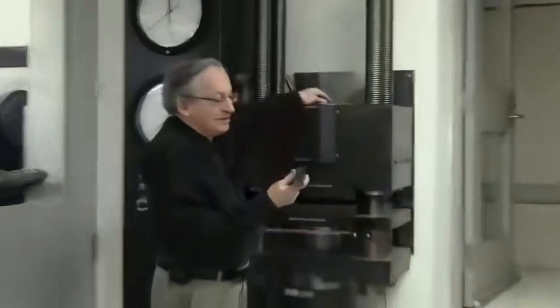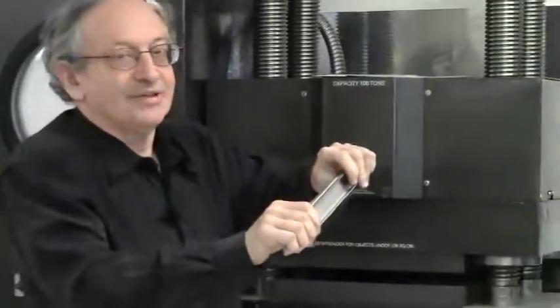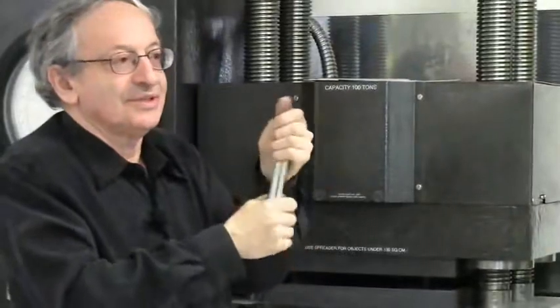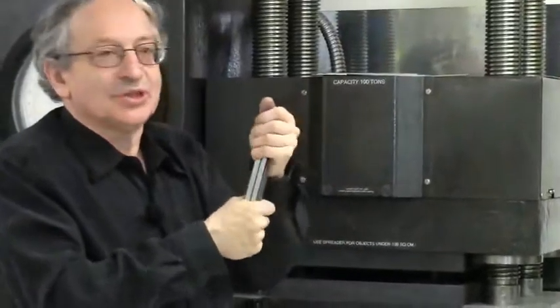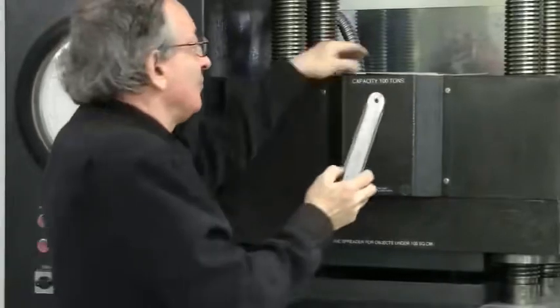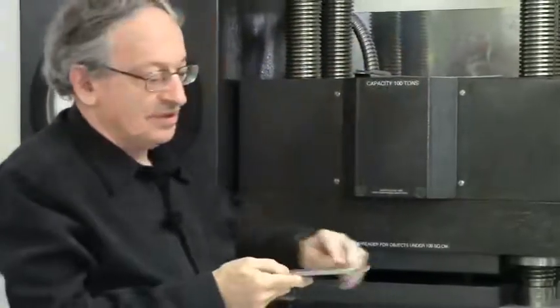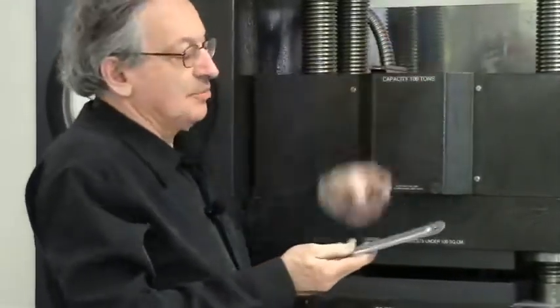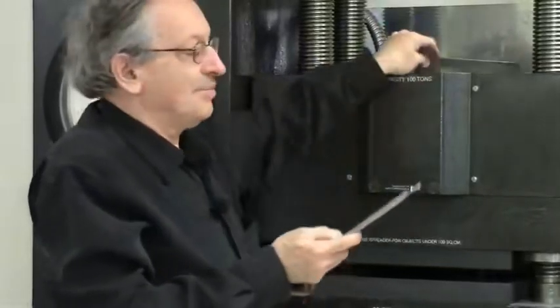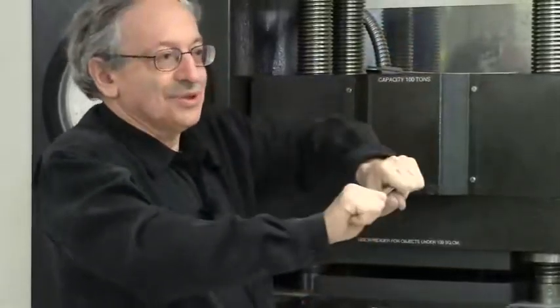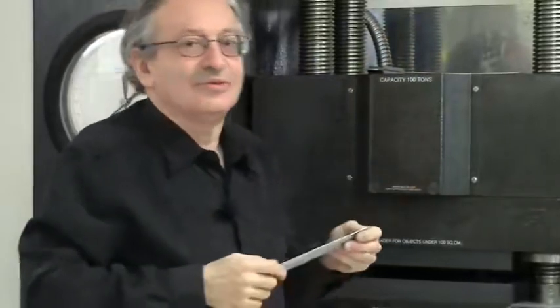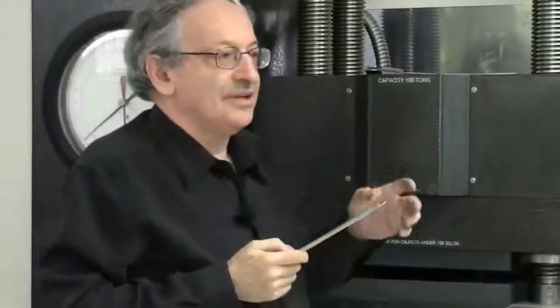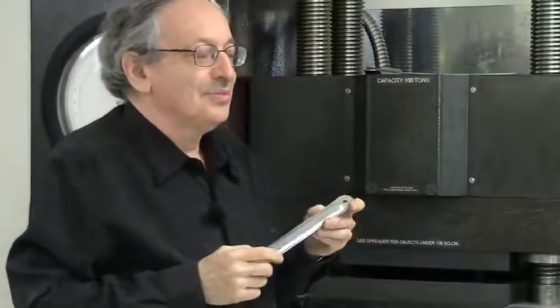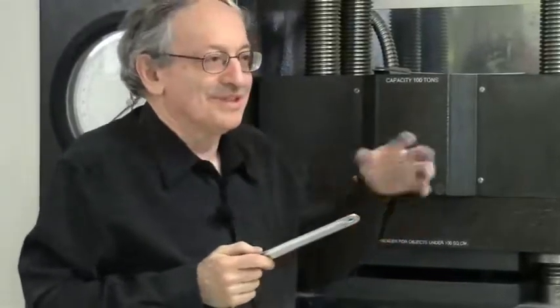without a press, it's also very strong this way, but it's not strong torsionally. I can still twist it. But to get it strong torsionally, you need a closed shape. So if you press in with a press 2 ribs, and then spot weld around the edge, you end up with something which has exactly the same weight, but it's stiff in bending, it's stiff torsionally. Okay, so if you're really concerned about lightweight, strong structures, you probably need to use presses somewhere, press in ribs,